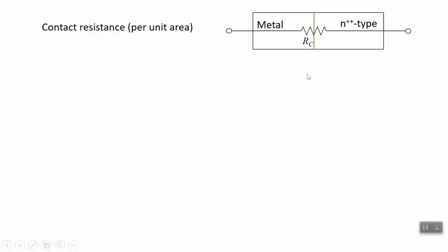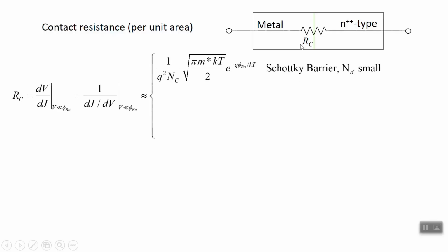It's usually reported in ohms per area. It's a dynamic variable. It's the derivative of voltage with current. So we'll say dV by dJ, so you have ohms per area. Or you could say dV by dI and just have ohms. I can do dJ by dV because we have an expression for J, a function of voltage. So you take the derivative of that function, invert it, and evaluate it at low voltage. Take the limit that voltage is really small.